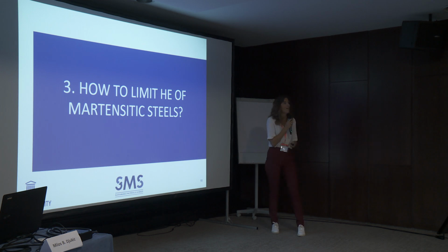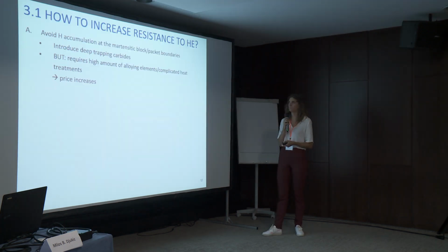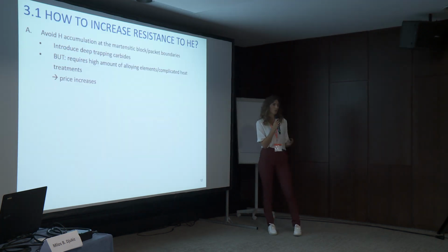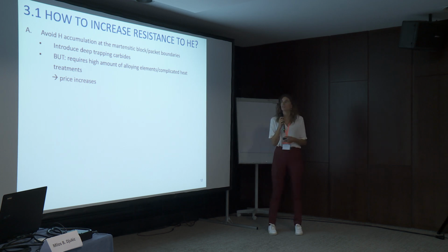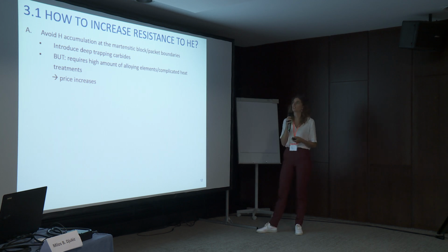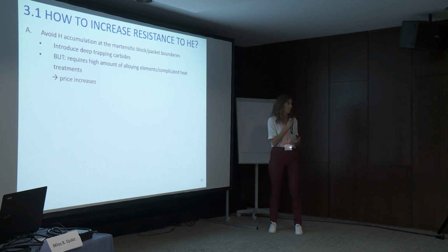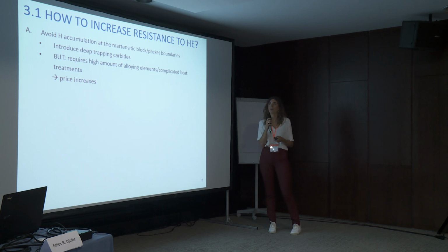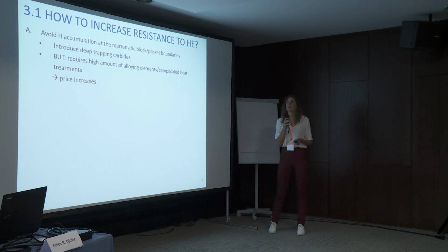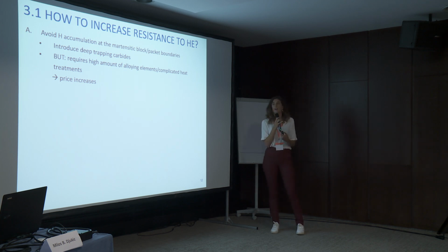So as a second part, I will propose to you now how we can limit the hydrogen embrittlement behavior of these martensitic steels. One way to do so, which is most commonly described in literature, is to introduce deep trapping sites. By introducing deep trapping sites, we can avoid the hydrogen accumulation at the martensitic blocks and packets. So this is very beneficial. However, this also requires a high amount of alloying elements and complicated heat treatments. This increases the price, which is not always a valuable option.